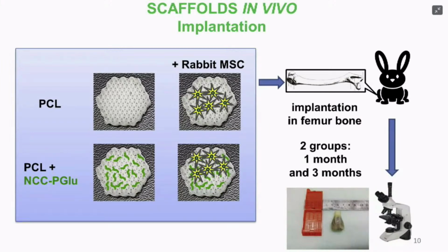There were 4 groups of animals and 4 groups of materials. There were pure polycaprolactone, polycaprolactone with polyglutamic acid modified nanocrystalline cellulose, polycaprolactone seeded with rabbit mesenchymal stem cells, and polycaprolactone with polyglutamic acid modified nanocrystalline cellulose seeded with rabbit mesenchymal stem cells. We could say that this sample is the most promising for the best results, because here we used the filler as well as seeded cells on top of it prior to implantation. The defect in the bone was 5 millimeters in depth and 3 millimeters in diameter.